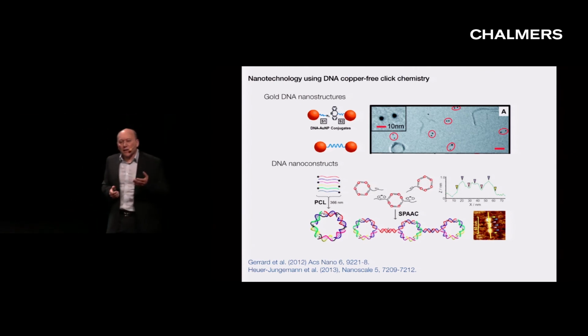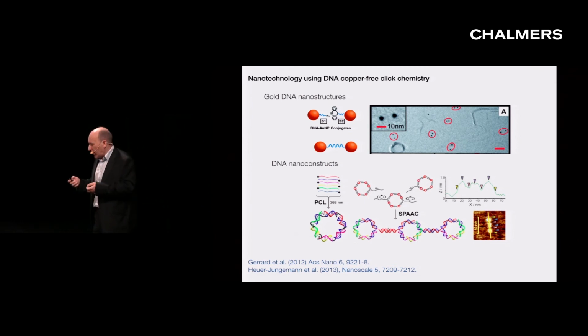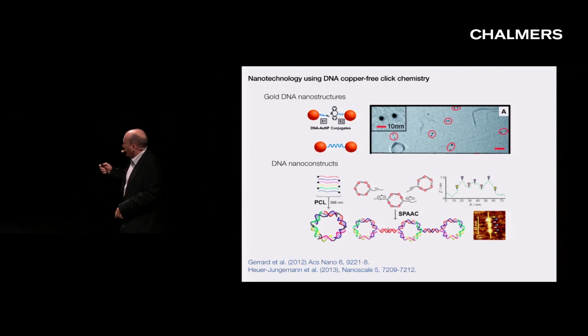Now, the way that we synthesized these gold nanoparticle DNA conjugates was to add a single DNA strand to each nanoparticle, using a very highly dilute DNA and using gel electrophoresis to separate the nanoparticle with a single DNA from nanoparticles with lots of different DNA strands around them. So you could say that this nanoparticle is a monovalent gold nanoparticle where the chemical bond is coming from the DNA strands that we're holding together.